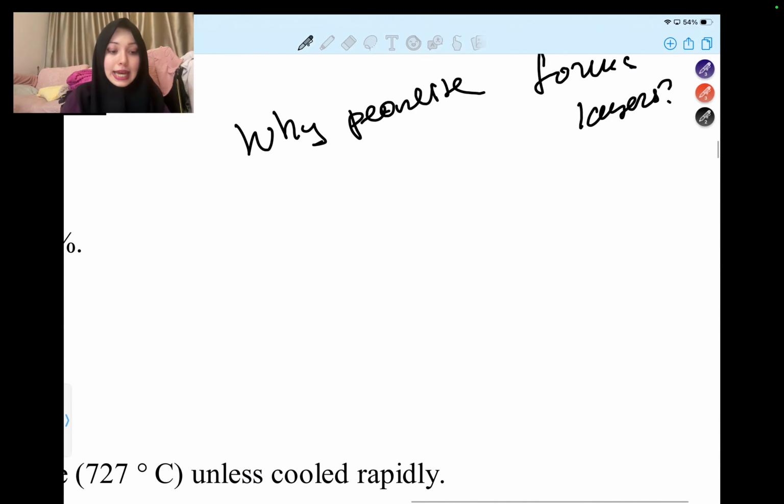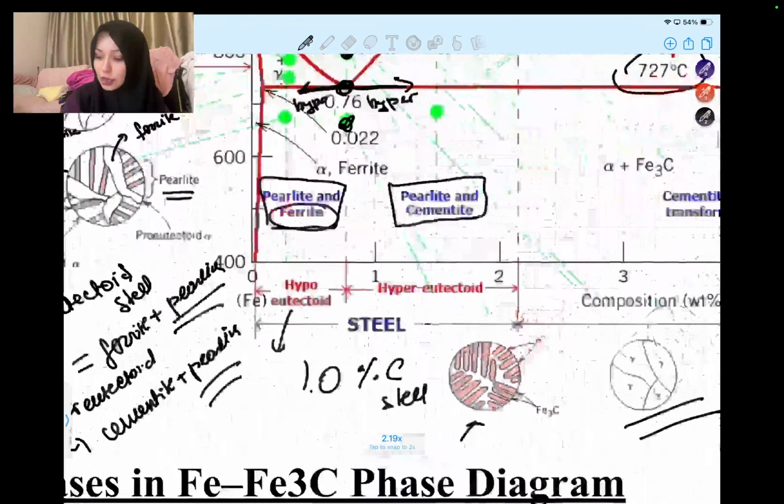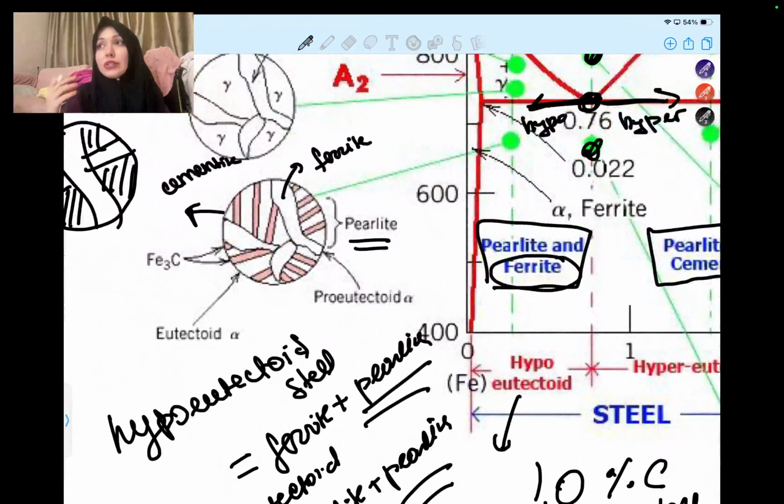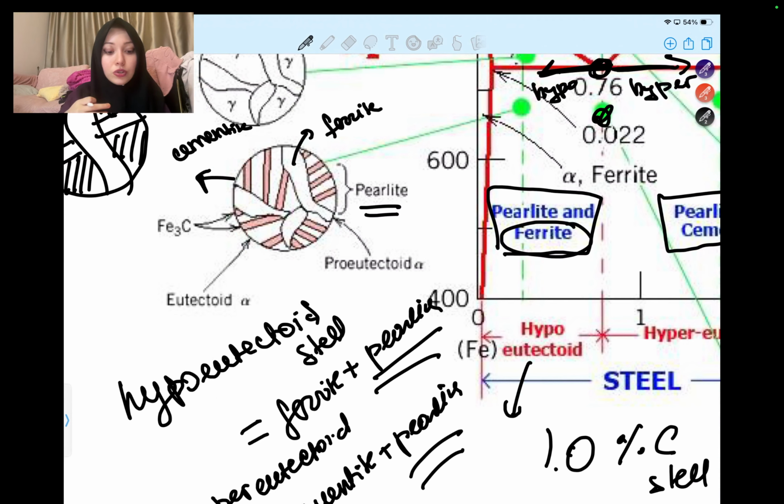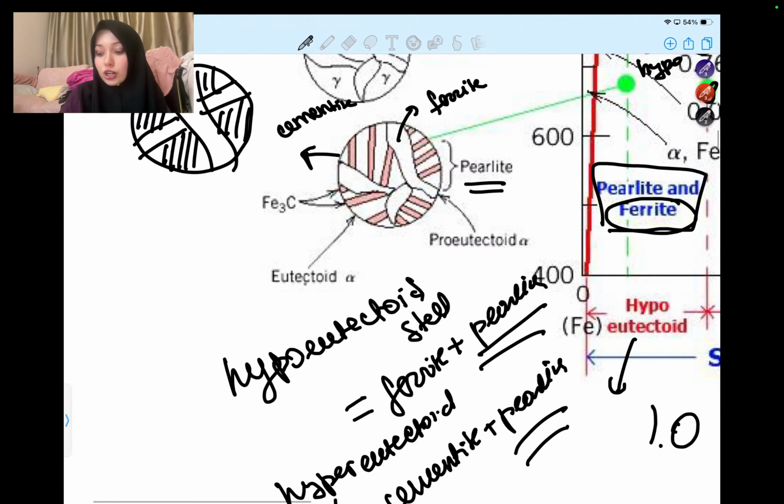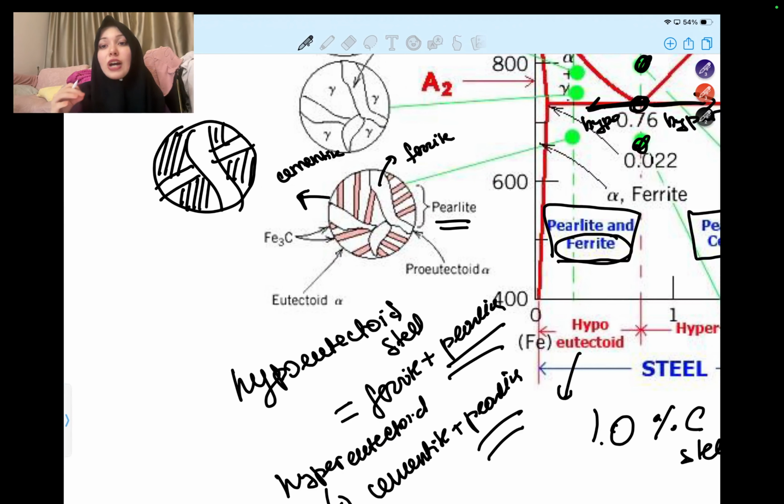So austenite has medium carbon, and when it transforms, ferrite wants almost no carbon, but cementite needs a lot of carbon. So here we have kind of opposition. The ferrite does not want carbon, but cementite needs carbon. So our carbon atoms must diffuse, and the structure organizes itself into alternating layers, so carbon does not need to travel far. And that is why the pearlite structure becomes striped.